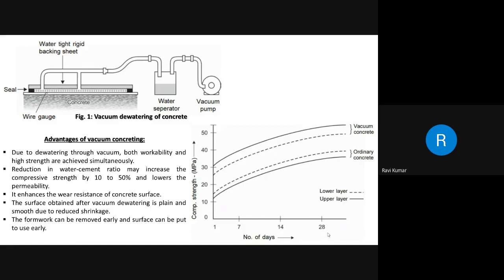Vacuum concrete is the type of concrete in which the excess water is removed for improving concrete strength. The water is removed by use of vacuum mats connected to a pump. That is a pictorial representation which I have shown at the top of this slide. This technique is applicable in industrial floors, parking lots, deck slabs of bridges, etc. The magnitude of applied vacuum is usually about 0.08 MPa, and the water content is reduced by up to 20 to 25%. This reduction is effective up to a depth of about 100 to 150 mm only.